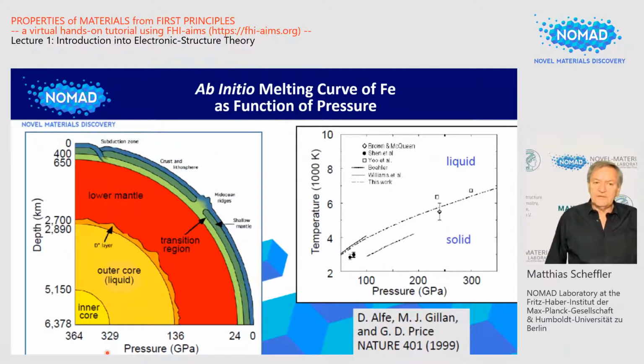Beyond calculating the melting curve, the authors also studied the viscosity of the material. The previously existing experimental estimates differed by many orders of magnitude. The DFT work showed that liquid iron in the outer core should have a local coordination similar to that of the HCP structure, and the viscosity is only a factor of 10 higher than that of liquid iron at standard on-Earth pressure conditions. This is actually on the lowest side of the previous experimental estimates.